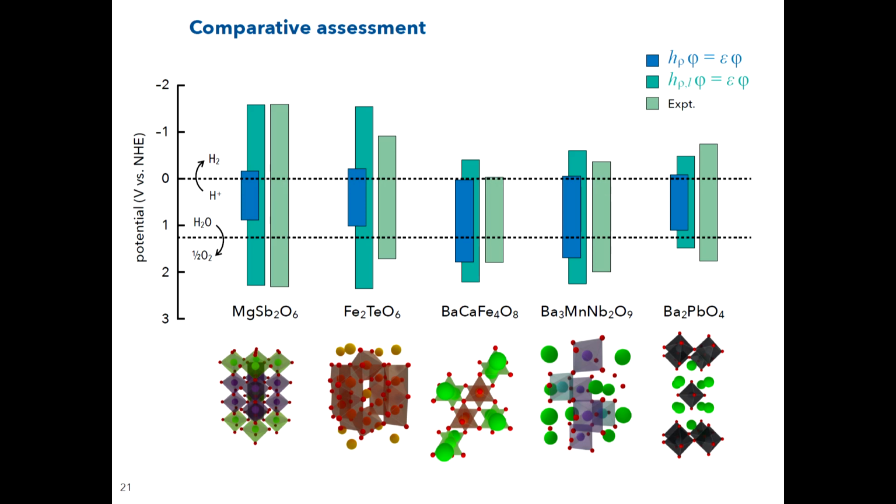So what we see here is that we tend to overestimate the band gap using this technique, as opposed to the regular DFT without the U, the semi-local or the local DFT, that underestimates the band gap. And here, what we found is that in most of the cases, let's say 6 times out of 10, you will find yourself in this situation.